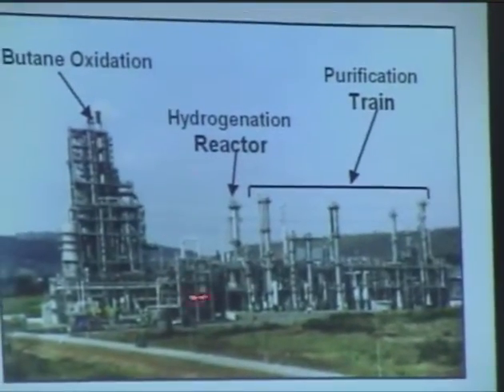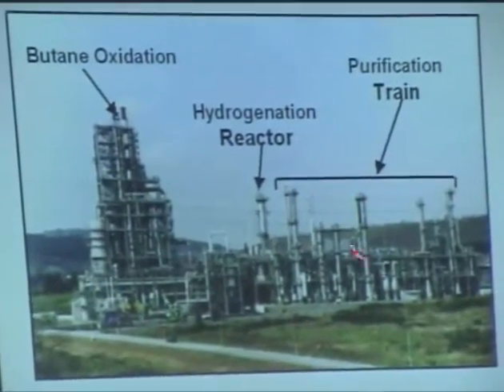We then commercialized the process in Asturias, Spain in September of 1996. And you can see this is a layout of the plant, a photograph of the plant, not a very good one. But here's the riser reactor to take the butane to the maleic anhydride, which is quenched as the acid. And then the hydrogenation reactor and the purification is all down here.